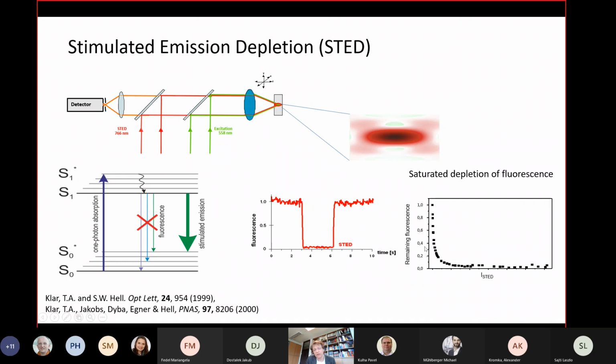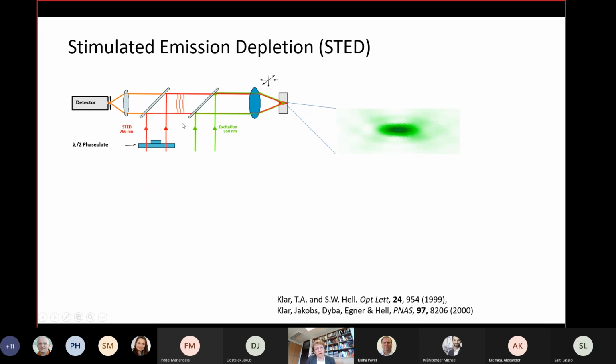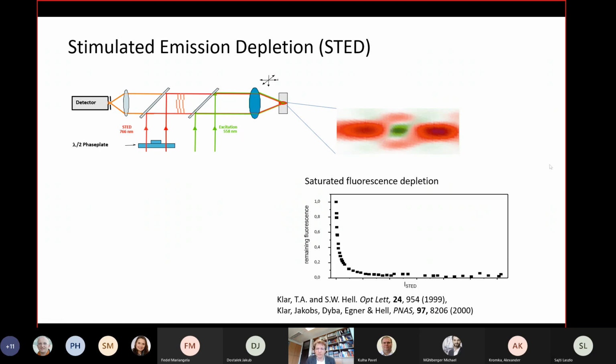And a very important graph is this one here, where I show the red intensity and the remaining fluorescence. The remaining fluorescence is the tiny little bit of fluorescence here. And you see that as a function of the red power or intensity, you suppress the fluorescence in a very nonlinear way. That doesn't improve your resolution by itself. So the original idea was to place this suppression in the outer rim of the focus, but not on top of the focus. And one can do that simply by playing around with the phase of the red light, which you put into the objective lens. And that allows you to create a focus that has a hole in the center. Okay, and now what is the size of the hole? The half width of the hole is of course given by the wavelength divided by 2. So that doesn't bring you much of an improvement, but there is this curve, okay?